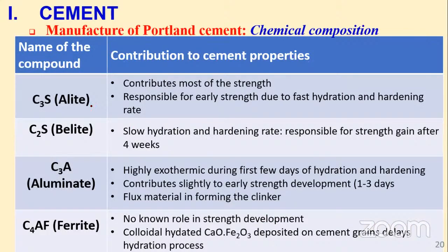And I need to mention here that there is a general English name for each of these compounds. The tricalcium silicate is referred to as alite, the dicalcium silicate, belite, the tricalcium aluminate is called aluminate, and of course, ferrite is tetracalcium alumino ferrite. Okay. Now, each of these has a contribution to the properties of cement. And as you can see, the tricalcium silicate contributes most of the strength. I remember it had 50%, because this explains the reason why we need it in high composition.